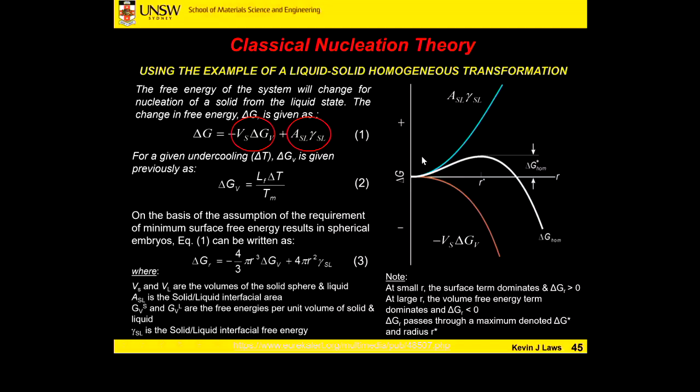So these are just the two components of our delta G calculation. The blue one is this component here, and it's always positive. It's trying to stop the reaction progressing. This orange line here is this part of the equation. It's always negative, so it's trying to move the reaction forward. Basically, this line here is just this one plus this one. Because this one starts to move faster than this one, we start to get the total of that reaction event going forwards, or to more negative.